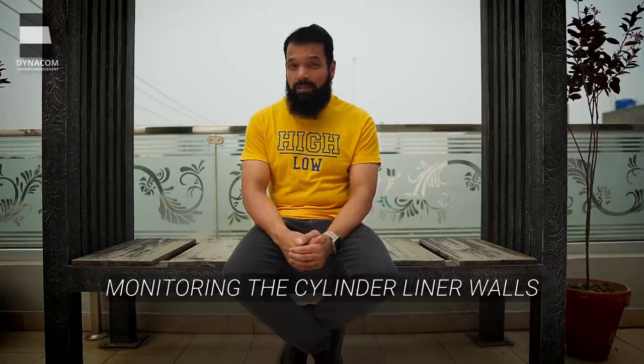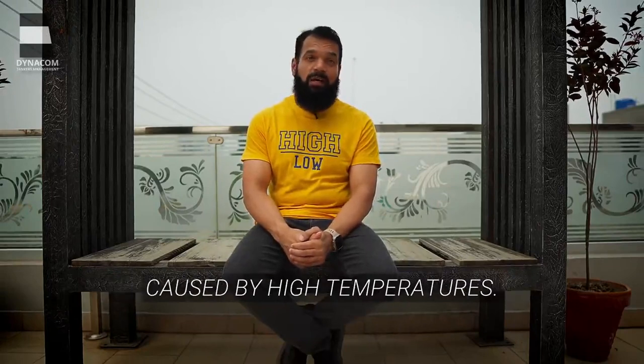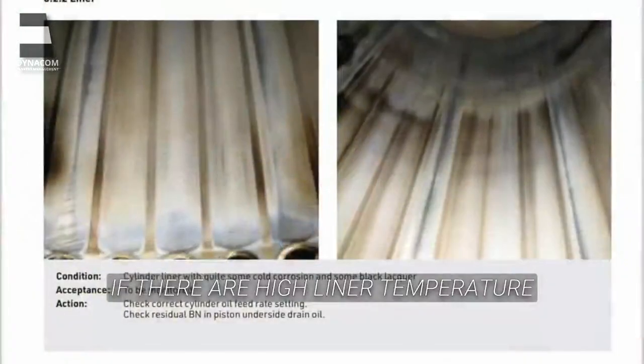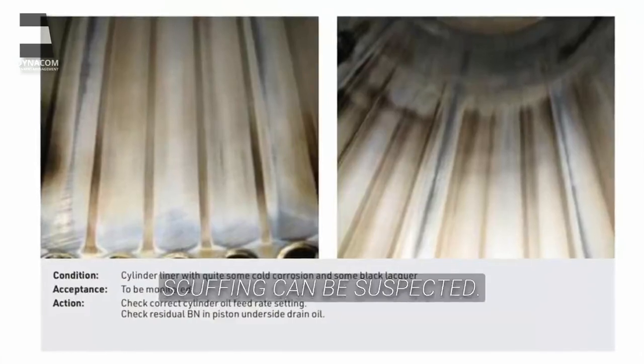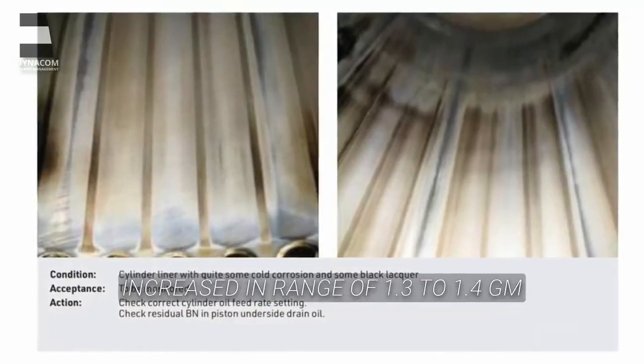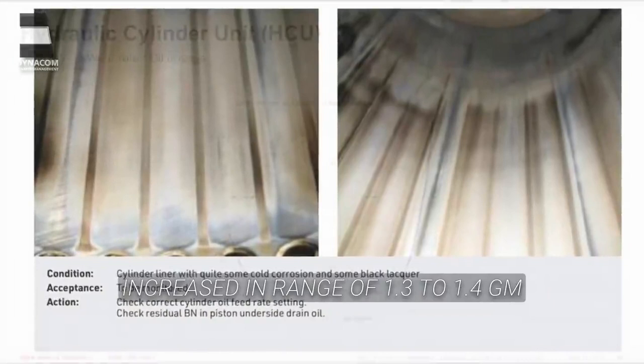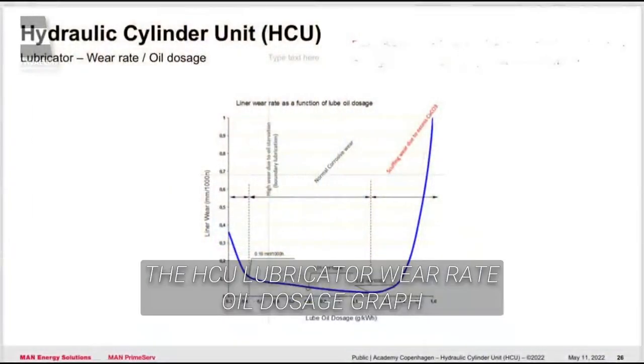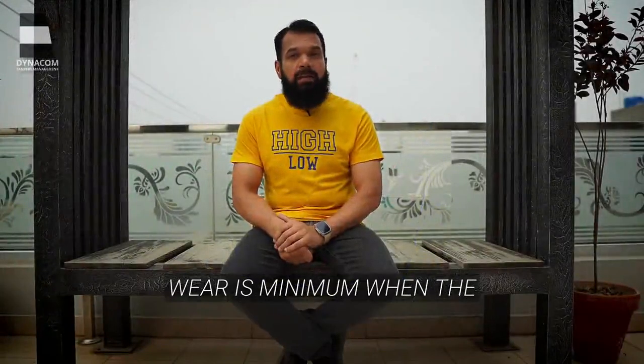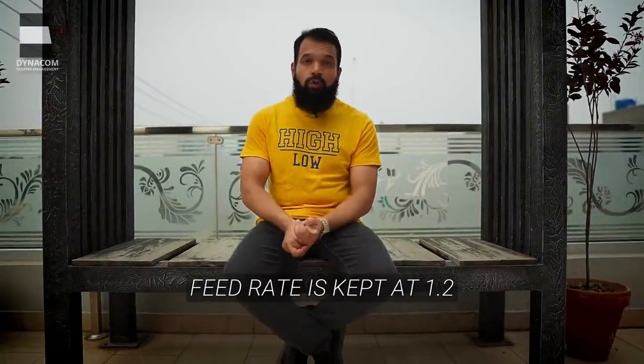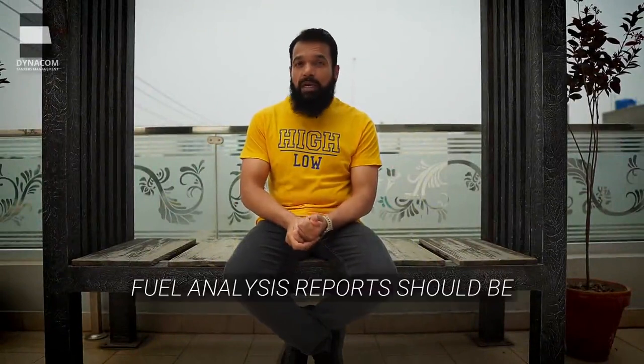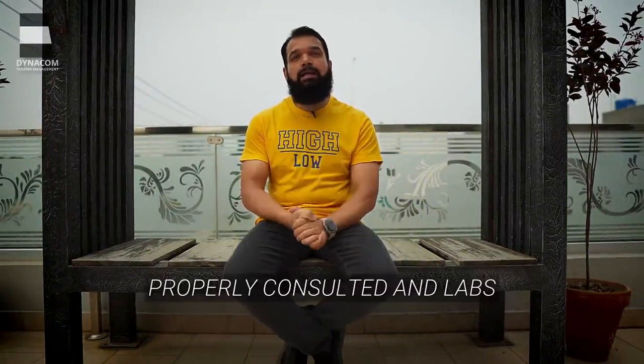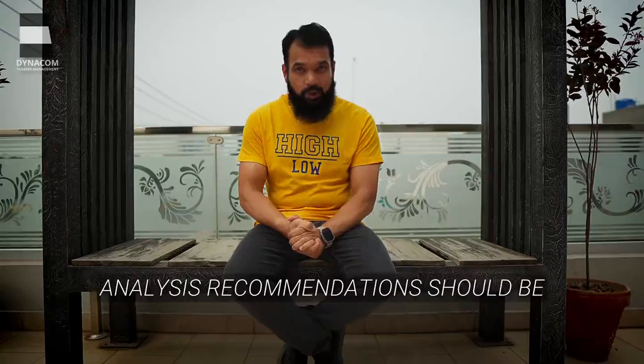Monitoring the cylinder liner wall's temperature can prevent scuffing caused by high temperatures. If there are high liner temperature fluctuations, scuffing can be suspected. Cylinder oil feed rate to be increased in range of 1.3 to 1.4 gram per kilowatt, as shown in the HCU lubricator wear rate oil dosage graph. For ME electronic engines, cylinder liner wear is minimum when the feed rate is kept at 1.2 grams per kilowatt hour. Fuel analysis report should be properly consulted and labs analysis recommendations should be followed.